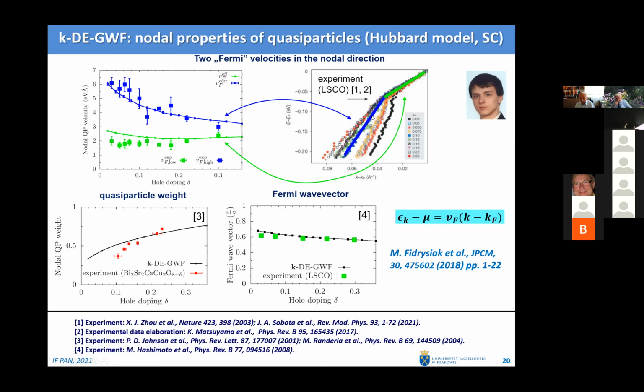And here is already a photoemission spectrum. What is a photoemission spectrum? This is the intensity of scattered photons, and this is the photoelectric effect. This is the kinetic energy of electrons coming from the absorption of photons, and it's the difference between the actual energy of the electron, which is taken out from its level, with respect to the Fermi level, and then this is the wave vector, which is momentum with respect to the Fermi momentum. So here you have Fermi level and Fermi momentum, K minus Kf equals 0, and you can see that it's practically universal, this Fermi velocity in the full doping range.